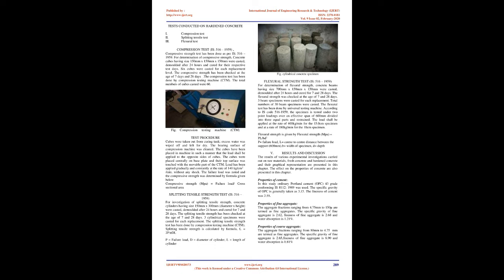It was observed that by using 20% of crushed brick the compressive strength increases, whereas by using 25% of crushed brick the compressive strength decreases. The increment in compressive strength at the curing age of 7 days was found to be 17.62% over normal concrete, obtained at 20% replacement, whereas at 25% replacement the decrement in compressive strength was found to be 1.277% than that of normal concrete.